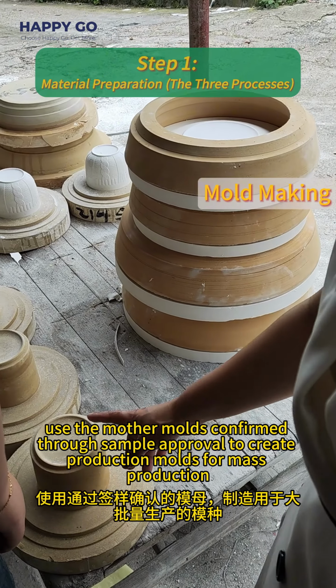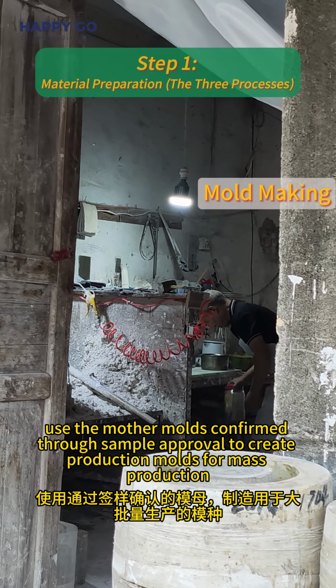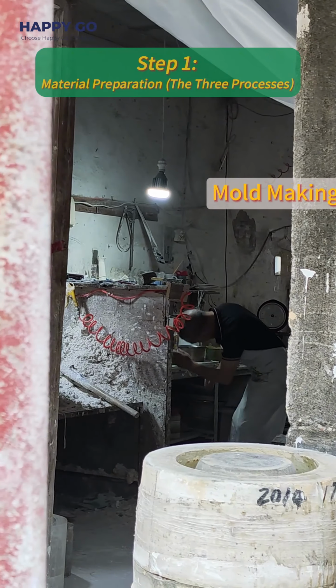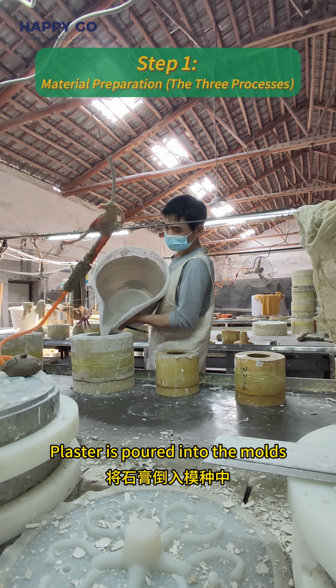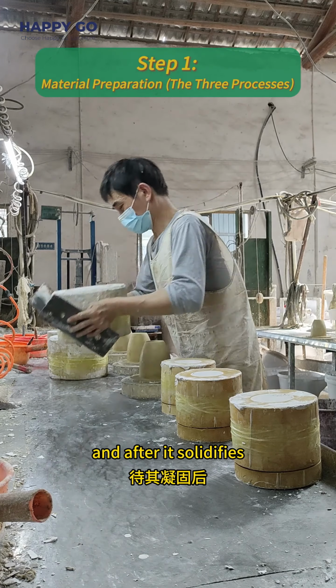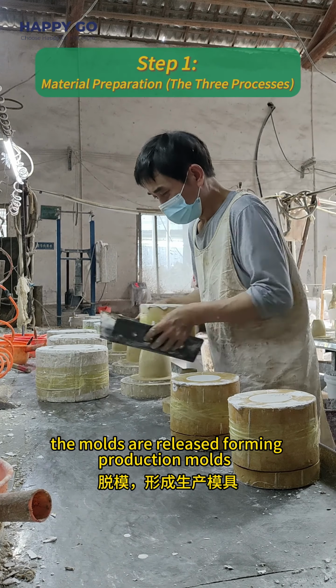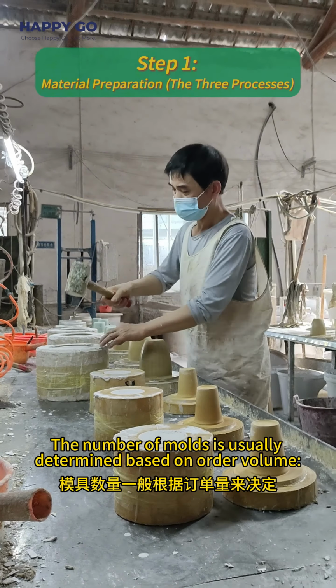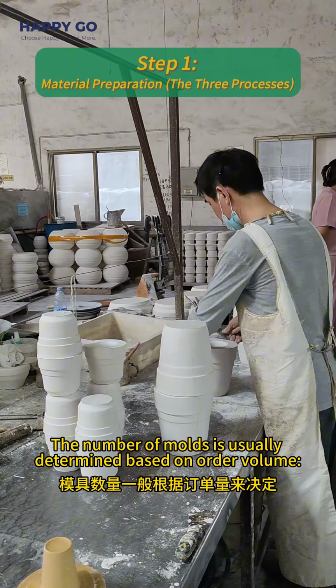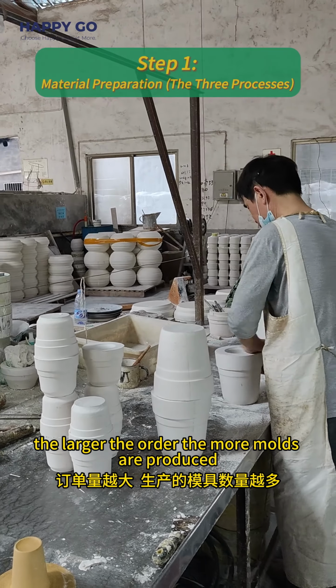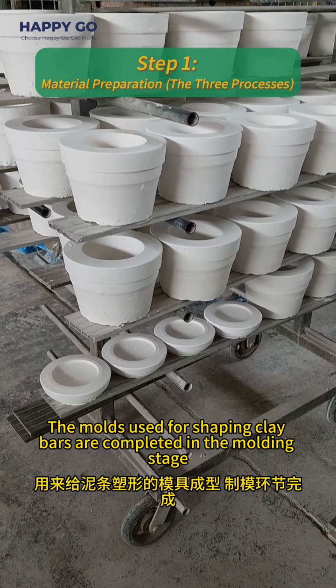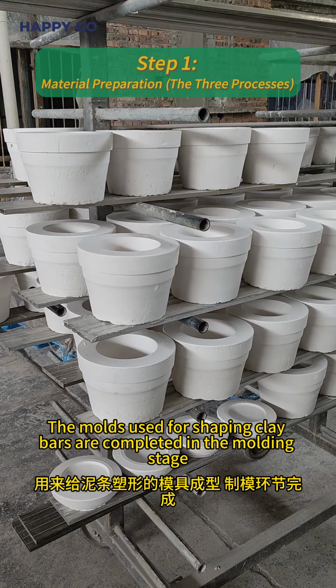Meanwhile, the mother molds confirmed through sample approval are used to create production molds for mass production. Plaster is poured into the molds, and after it solidifies, the molds are released, forming production molds. The number of molds is usually determined based on order volume. The larger the order, the more molds are produced. The molds used for shaping clay bars are completed in the molding stage.